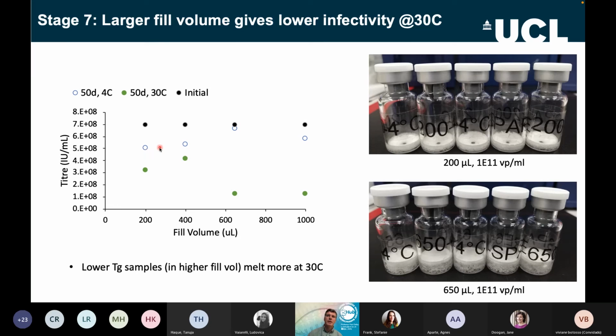But the main result is that the higher fill volume has really quite severe drops at 30 degrees, which tells us these aren't very stable at all compared to the lower fill volume ones. Again, we need to see the error bars before we can judge exactly where they stand, but it seems that the samples with lower Tg, in the higher fill volume, melt more at 30 degrees C, and that's losing infectivity. So a viable way forward is to reduce the fill volume to 200 microliters. I should add, this was done with one of the older processes, which has since improved, so the cake appearance is generally better. This was done with the earlier step annealing, the step temperature change.